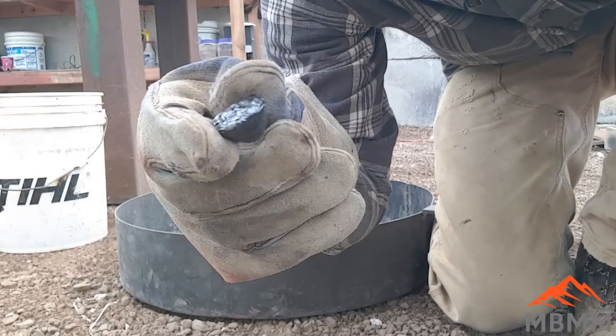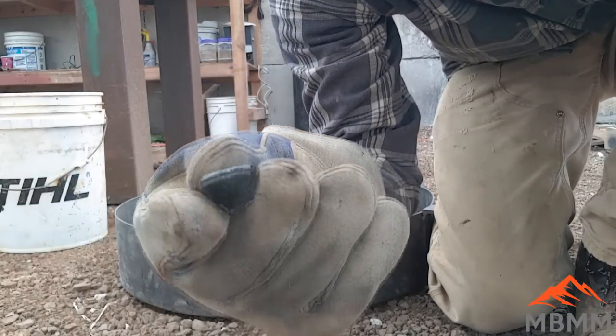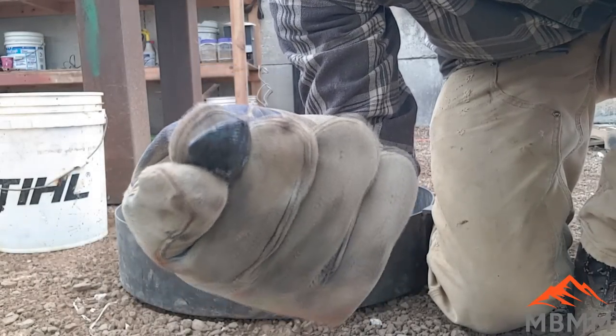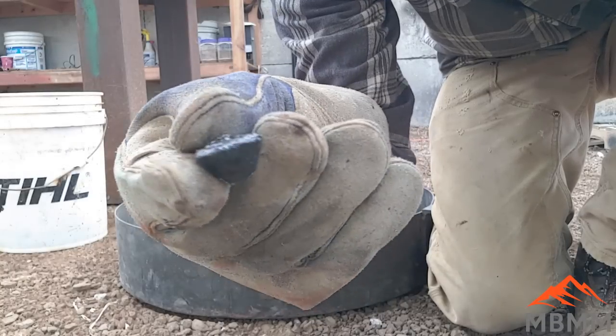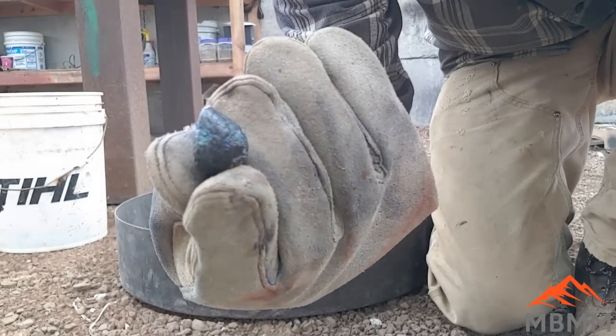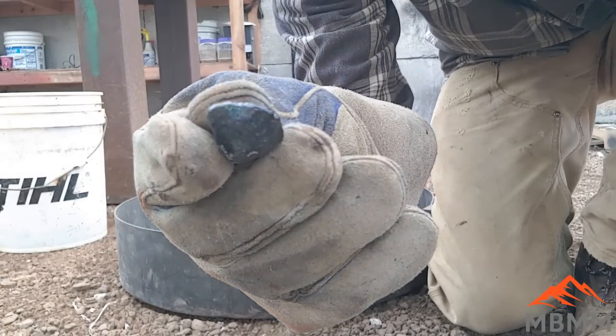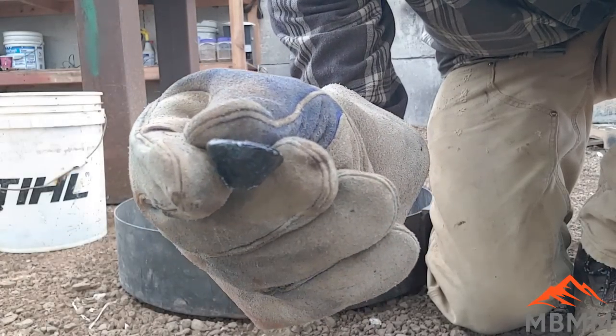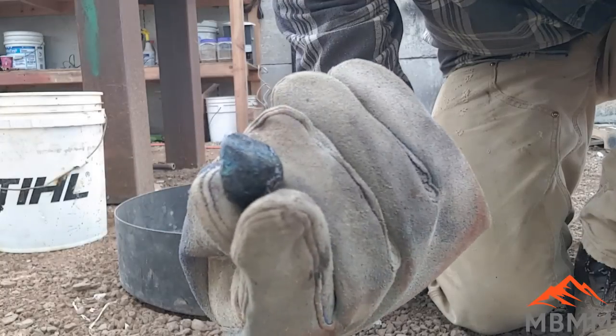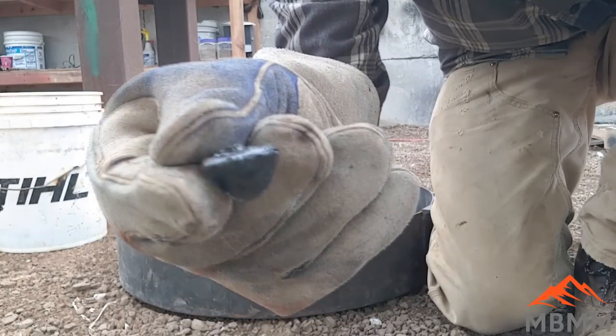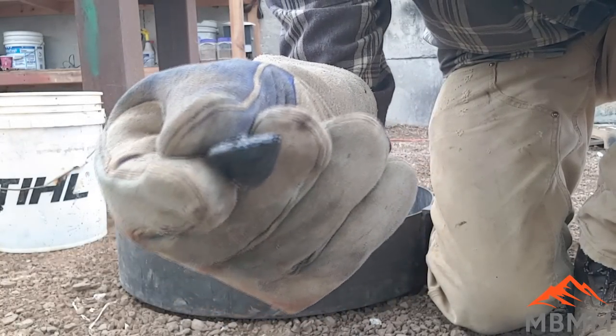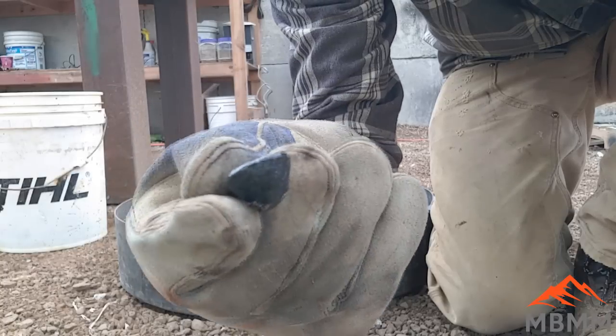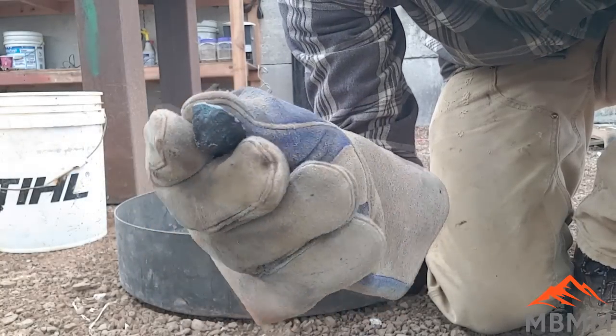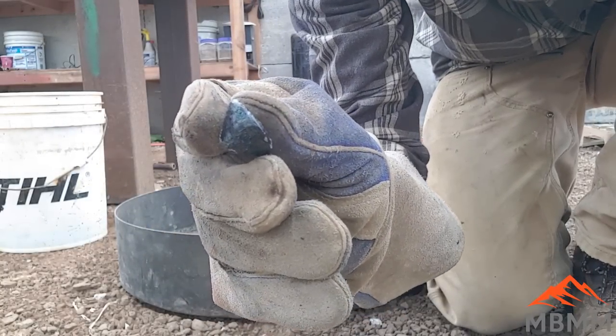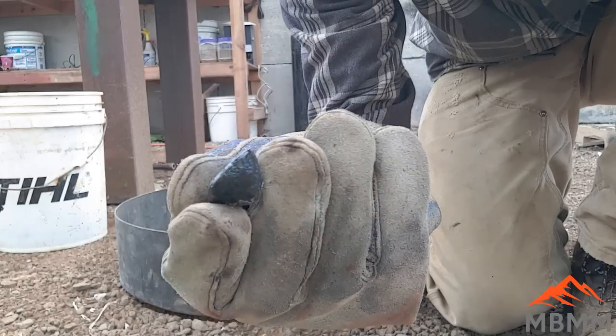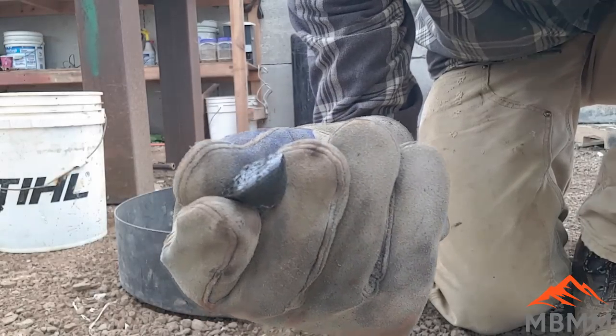Anyway, it might be hard to tell in the video, but it's just a lead button. There's no matte on top. It just goes glassy slag all the way down to the lead. So that was a good decomposition of those sulfides. And the iron bar really helped to take all those other base metals and sulfides, turn them into FeS, and then dissolve them into that slag we made. So I'm going to take this, pound it into kind of a block so it knocks off a bunch of that slag, and then I'm going to put it in a cupel and put it in our furnace.